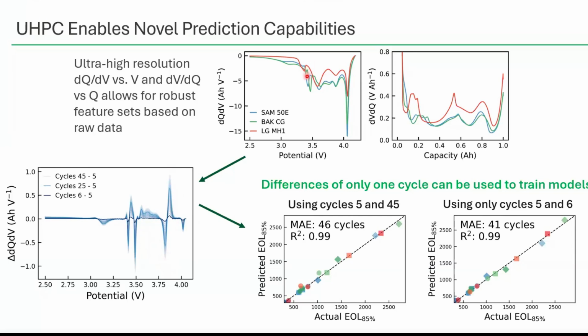This has to do with capacity fade, both at the anode and the cathode, depending on which peak we're looking at. And baked into all this raw data is all of that information about charge endpoint slippage and capacity fade, coulombic efficiency. So when we use this raw data and these features based on DQDV peaks, positions, magnitudes, and we use just that as inputs into lifetime prediction models, we actually get some really great performance in a very short